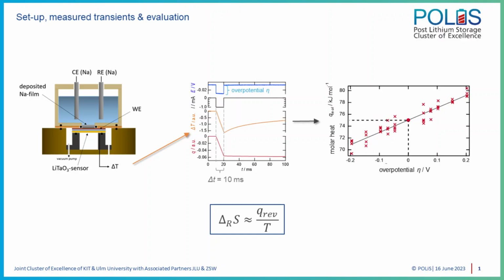The heat is determined by measuring the temperature change of the working electrode with a pyroelectric lithium tantalate sensor. And as a working electrode, we use thin copper foils, which were directly located on top of the sensor. On the copper foil, a thick sodium film was then electrochemically deposited before we started our measurements. And these measurements typically consist of series of 10 millisecond potential pulses with amplitudes between 50 and 200 millivolt and alternating signs, and always starting from the equilibrium potential of the system.